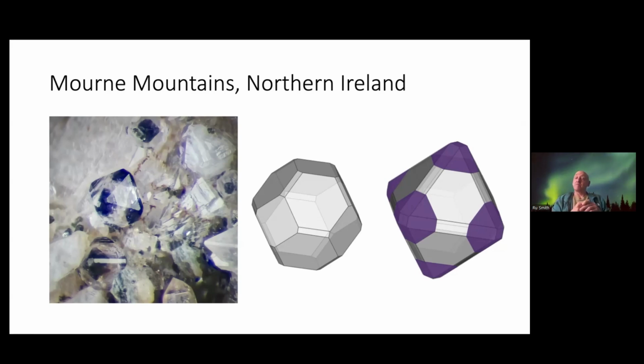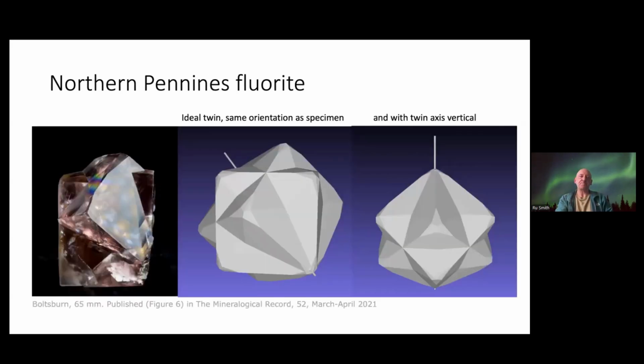And sometimes there are features that are temperature dependent. So with fluorite, probably at the lower temperatures, there's adhesion of water molecules to the cube faces of the fluorite, which slows those down, which means that they're prominent, and the other faces grow out. So there are lots of different things that can happen in nature, and those can override the normal, simple, structurally defined relative importance of the different faces.